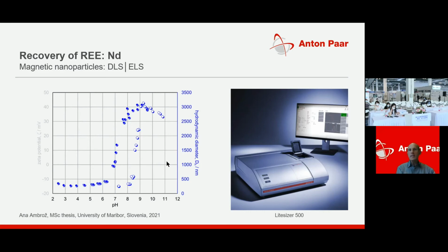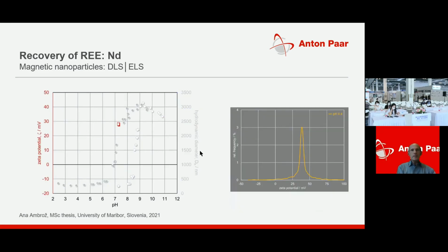How can we understand this hysteresis or the change in particle size with different pH? To elucidate this pH dependence, we determined the zeta potential in parallel by measuring the electrophoretic mobility of these particles.